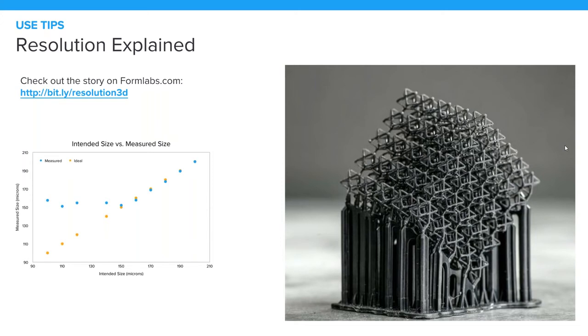However, before I move on from this slide, that is our minimum dimension, and we really recommend that it's only used for very small and very fine parts. In fact, we have a special castable setting specifically for jewelry that's optimized for fine detail. For the majority of our other parts, however, we recommend about 50 microns. For large parts, especially ones with flat sides, we really recommend 100 microns. Remember, these settings are for layer height. So unless you have a feature below 50 microns in height, you won't notice a difference between 25 and 50, other than a relatively small increase in smoothness of the part.